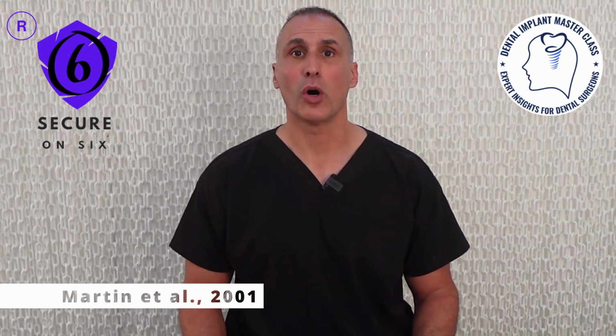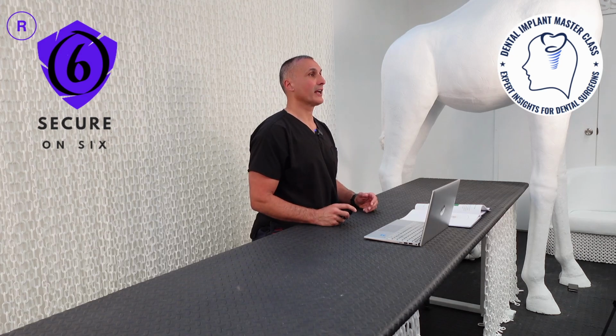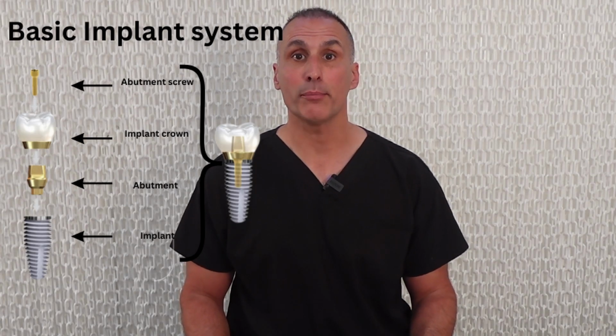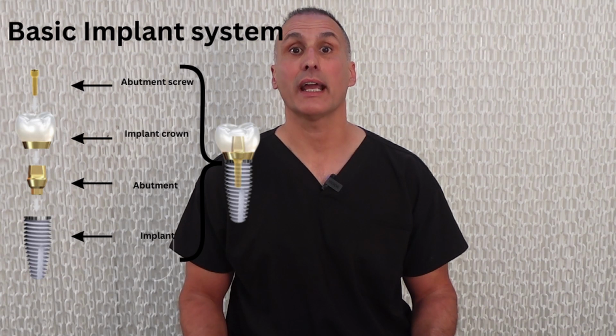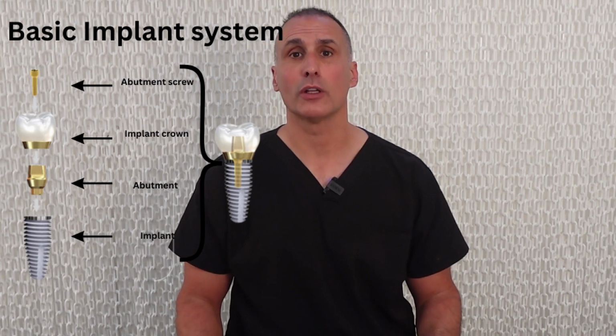In 2001, Martin also compared gold alloy abutment screws with 0.76 microns of pure gold coating lubricant over the screw flanks to other abutment screws and showed a greater number of mating thread contacts in the gold screws with gold coating lubricant. This finding was explained by either an increase in gold screw elongation or the higher preload value of gold abutment screws. A basic implant system comprises an implant crown, abutment screw, abutment and implant. And here is a graphical representation of an implant system.